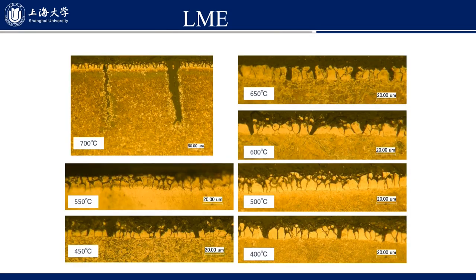The high temperature oxidation resistance of coated steel is better than that of the bare steel. The room temperature tensile strength of the formed specimen can basically meet the requirements. When forming above 700 degrees C, the melting point of the GA sample is higher than that of the GI specimen because the coating contains iron element, so the crack initiation and propagation are relatively slight under the same deformation conditions. The micro cracks are fewer and the propagation depth is shallower.